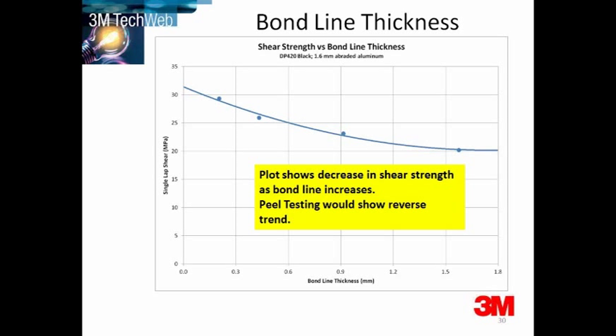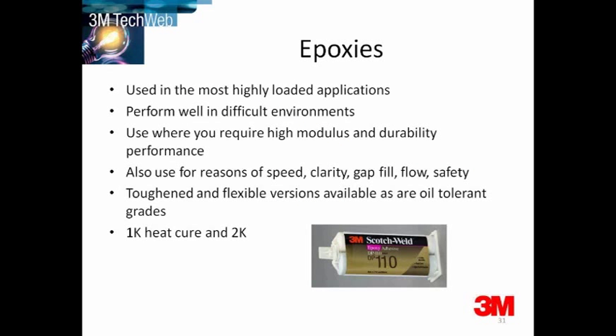There are many different adhesive types. I'm going to quickly go through the features and benefits of the main adhesive types for structural bonding applications. Epoxies are generally the adhesives of choice in the most highly loaded applications — they are typically the strongest adhesives available. They perform well in difficult environments, are available in a variety of moduli and cure speeds. Toughened and flexible versions are available, as are oil-tolerant grades, in both one-part and two-part forms.